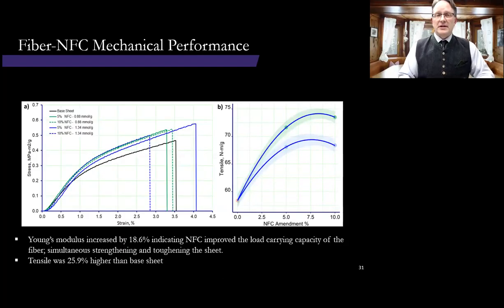Now, our mechanical response for the reinforced paper was measured using a tensile tester. These solid lines in this graph represent the low percent NFC, and the dashed lines are the high percentage of NFC, with green being the low charge and blue being the high charge. So at high charge, low concentration, we observed a large improvement in Young's modulus, about 18.6%. And what that indicates is that the NFC is improving the load carrying capacity of the fibers in the sheet, while simultaneously strengthening and toughening the sheet. And we see the same trend compared to the base tensile here in this right diagram. And as we increase the amendment level of the low, our tensile is increasing. And we've got about a 26% increase over the base sheet.